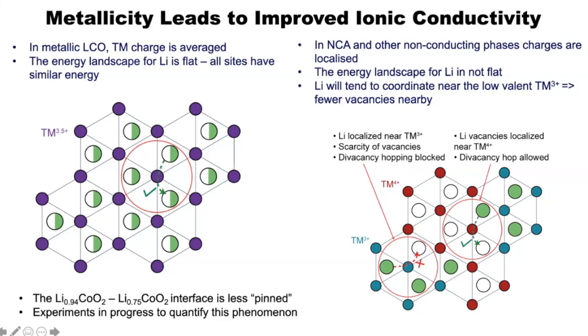lithium excess, you go back to this process where you have some first-cycle loss in coulombic inefficiency. But if you have a really stoichiometric material, you get very little pinning of this interface. And so you can get very rapid movement of the interface through the phase, and you don't see this behavior. And so experiments are in progress to quantify this phenomenon, particularly by looking at the lithium mobility in these materials.